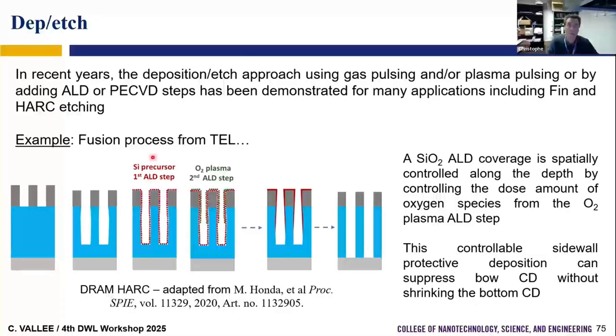Second step of improvement of what we do for the next generation of etching. So we'll probably develop more and more etching where we add a deposition step in the etching step. And the idea to add a deposition step is to have some corrective step. So for example, you do your high aspect ratio etching, and you may have some unwanted non-uniform profile, because you have ions reflecting, for example, from the mask, so you may have unwanted non-uniform etching.